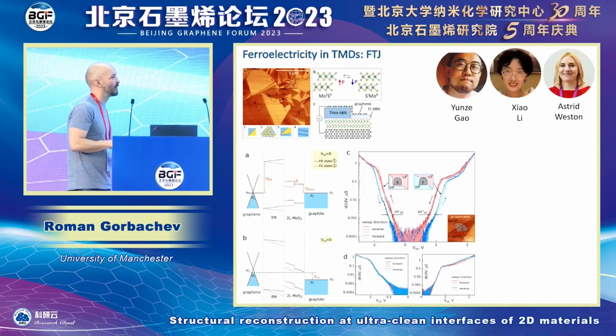And so, okay, so what if we try to construct a device out of that and make a ferroelectric tunneling junction? So this device is actually used in industry with classical ferroelectrics. Can we do this in 2D materials? And the answer is yes, but everything will be different. The way it is different now is that you do have this electric field inside that changes the way electrons tunnel through this dielectric layer. And depending on the polarization orientation, up or down, you can have either high tunneling current or low tunneling current.